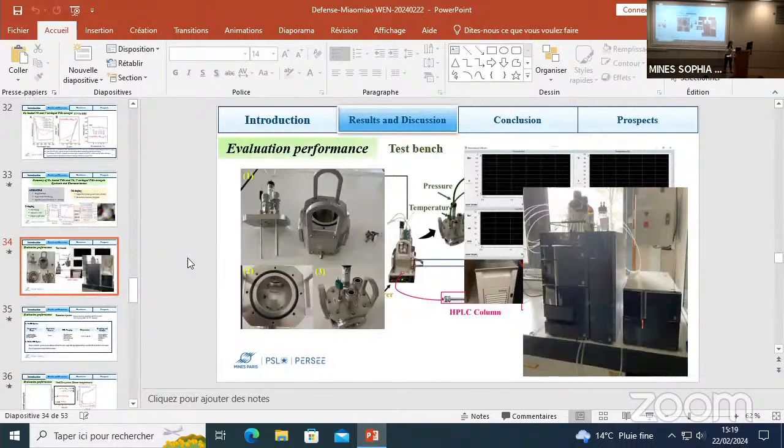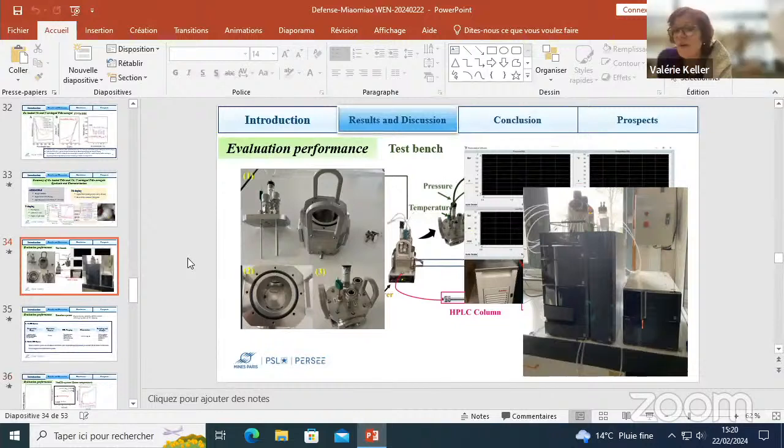Here the light we were using is a 100 watt xenon light, and at the beginning we didn't use a filter to cut UV, so we were using the full spectrum of our xenon light. We didn't measure the exact power, so we just know it's a 100 watt xenon light. But the 100 watt gives no information about the irradiance. It is just the electric power.